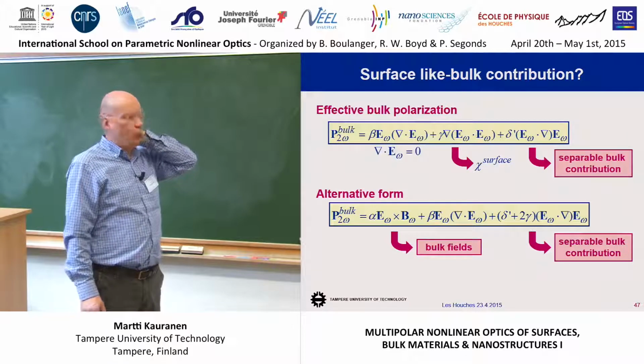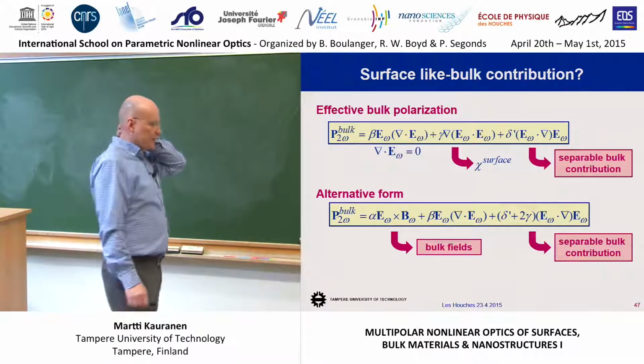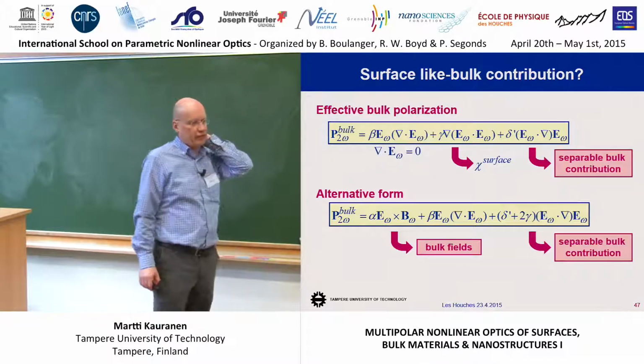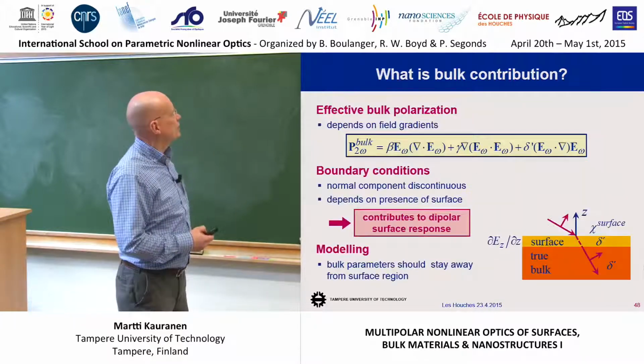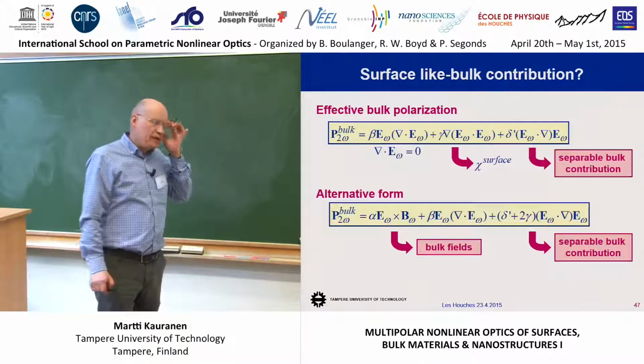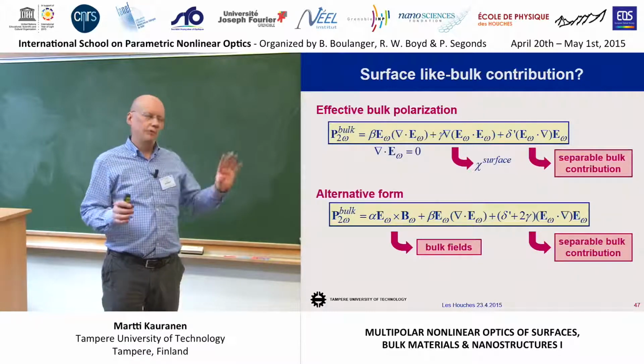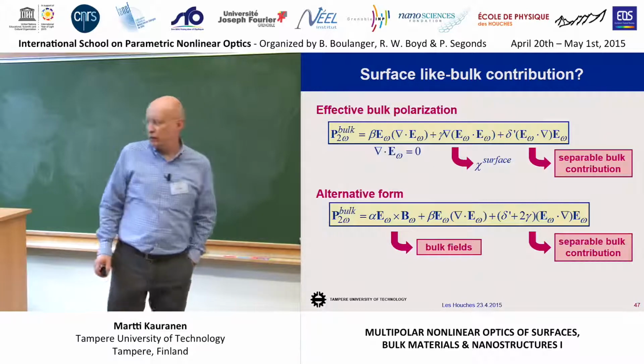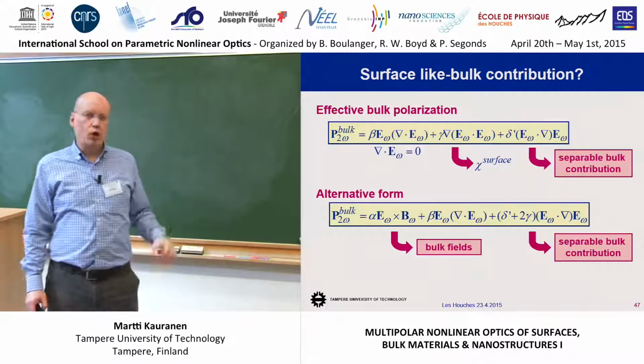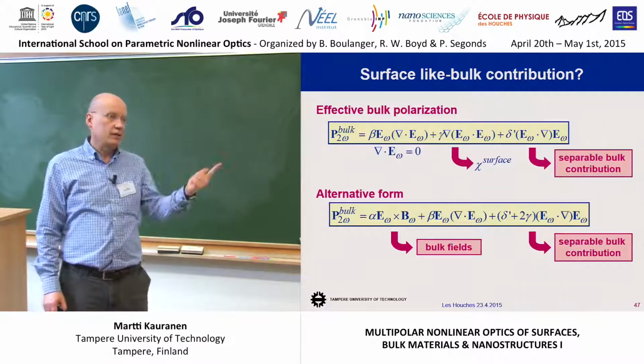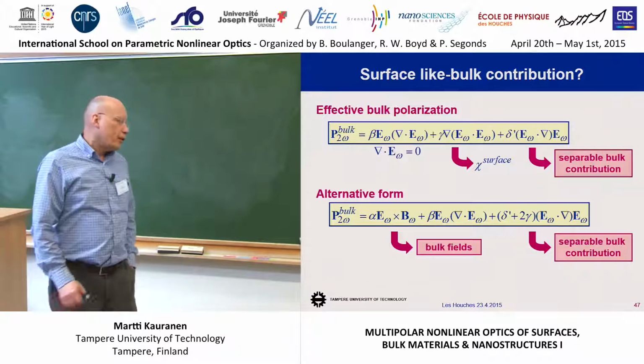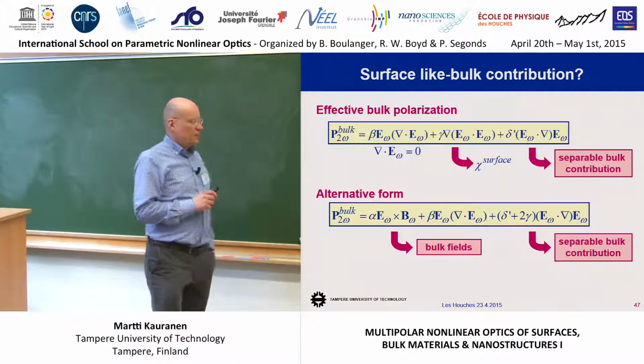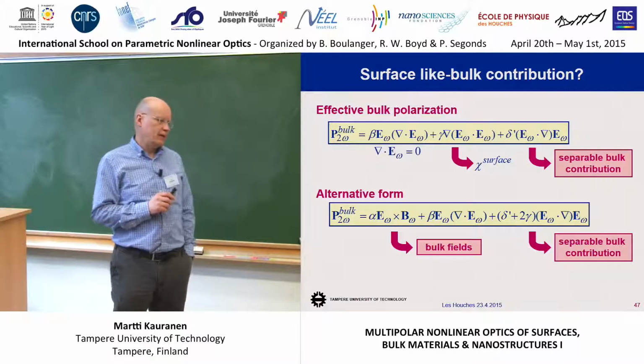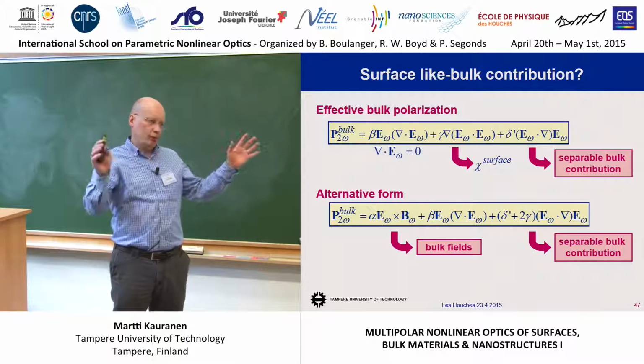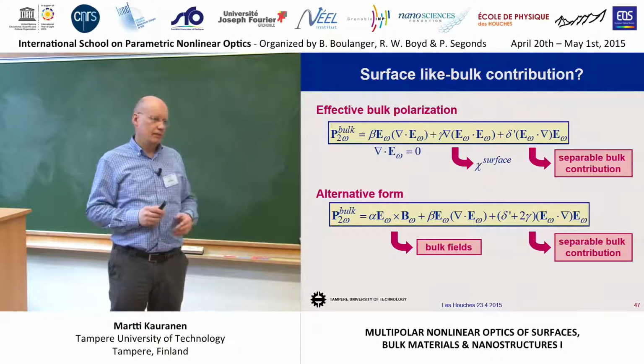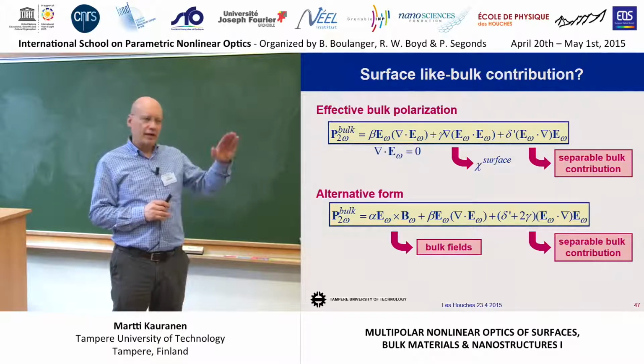The other thing which bothers me, I'll mention it already now, is that I don't really like this approach of effective polarization. I have to check what this other slide is. It's not this one, yeah. The problem with effective polarization is that, if you take Jackson's book or books on electromagnetic theory, you find out that you can define this effective polarization, which combines the dipole polarization, magnetization, and quadrupolarization. The problem is that the treatment is based on an infinite bulk medium. What we have here is basically finite media where you have interfaces and so on.